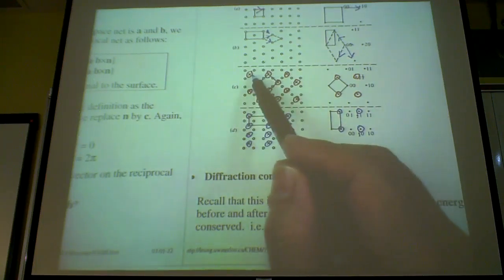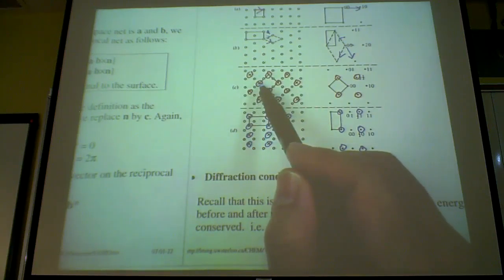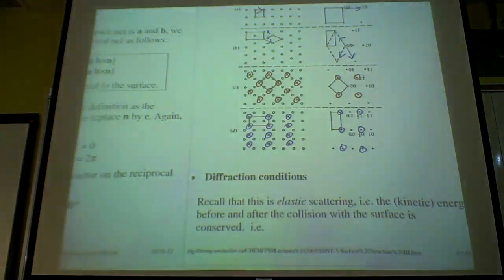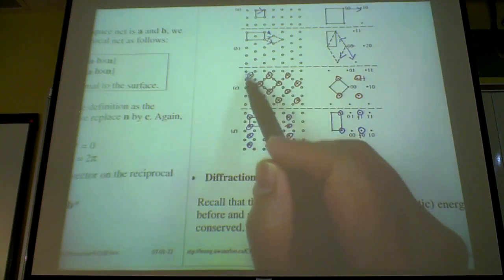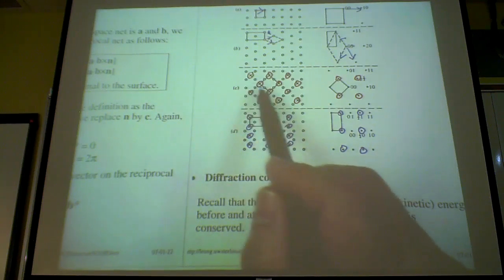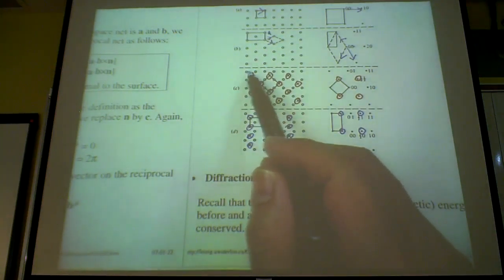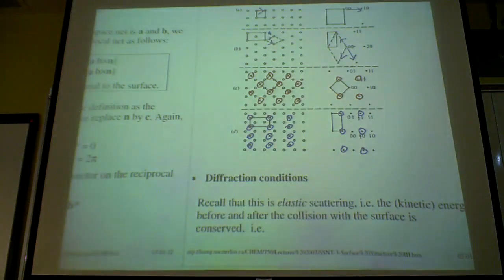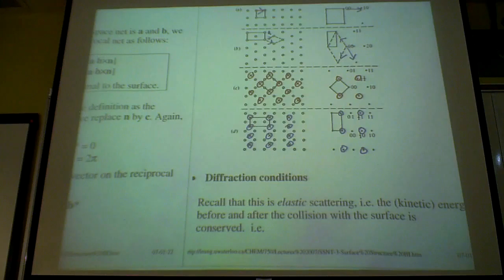So this would be my unit cell, but then I have a center spot in this unit cell. So this is a center 2x2. Because this here will be my 1x1, and here I have twice as long. It becomes 2x2, remember how we define twice as long with respect to my original grid. And because I have a center point in my square, it is the center 2x2.